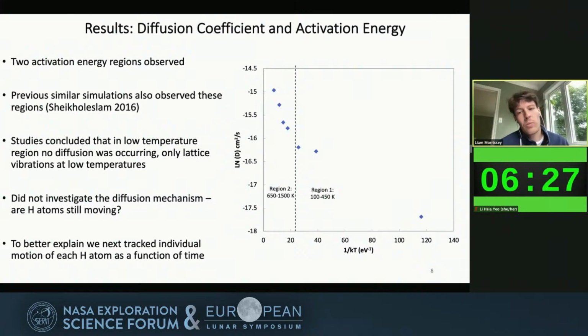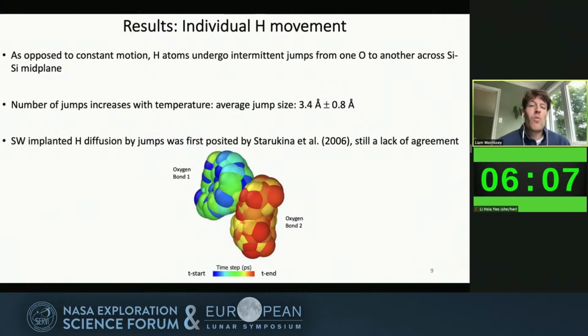The problem is that while these studies made this finding, they didn't actually investigate the mechanism of the diffusion, and were unable to answer the question of, are we just seeing limited motion or are we seeing no motion at all? So basically, we wanted to better explain what was going on here by tracking the individual motion of each H atom as a function of time. When we do this, we can get a better sense of the individual movement of each proton within that silicate.